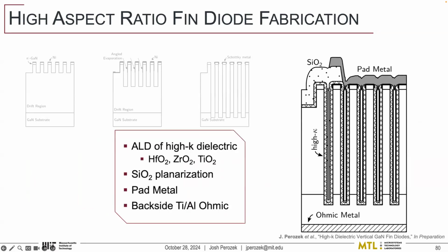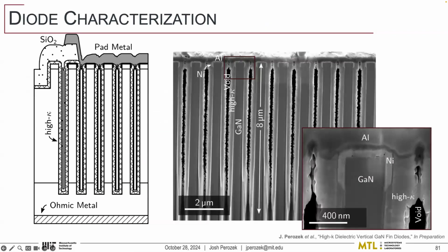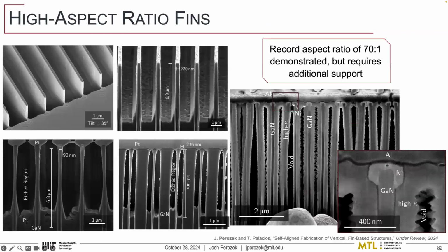But to finish off the devices, once we have those very tall fins, we just fill them with the high-K dielectric, we planarize it with oxide, we put on our pad metals, and we're able to actually make the devices. And with this technique, we're able to demonstrate the highest aspect ratio fins ever made in gallium nitride. They're about 70-to-1 aspect ratio in the most narrow case.